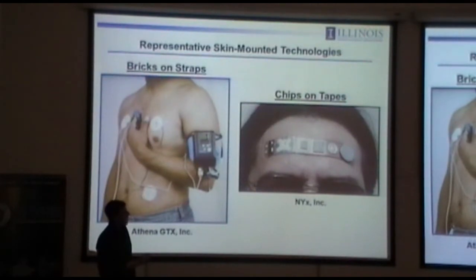And moreover, in order to get high signal quality, you typically use coupling gels that reduce the contact impedance between the electrode and the skin to enable high-fidelity recording. That gel dries out. The other aspect of this is that you have really separated the interface to the body from the electronics. As a result, you can't scale up the number of contacts. You have millions of transistors here, but only three contacts to the body. And that's obviously a deficient way to do integration.